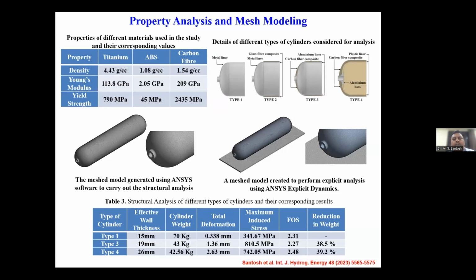While developing these cylinders, one of the interesting aspects we also tried and tested is: why should the cylinders be actually cylindrical in nature? Why don't we change the shape of the cylinder and try to come up with a different form? The basic problem associated with such a change in the design is that when the pressure is applied within the cylinder, the most vulnerable part of the cylinder is the sharp edge associated with it if we change the structure. Those sharp edges, like in a square or rectangular model, will eventually cause ruptures on the surface of the cylinder, due to which there is diffusion of the gas from the liner material.